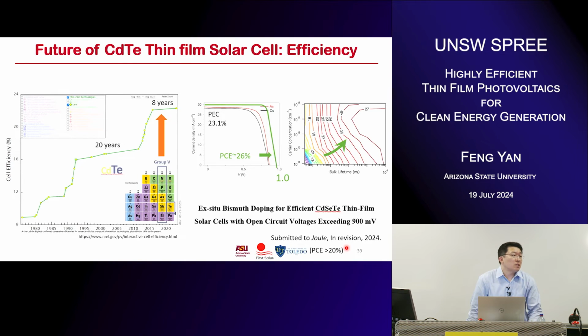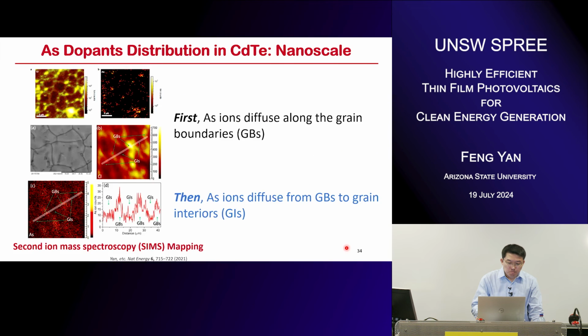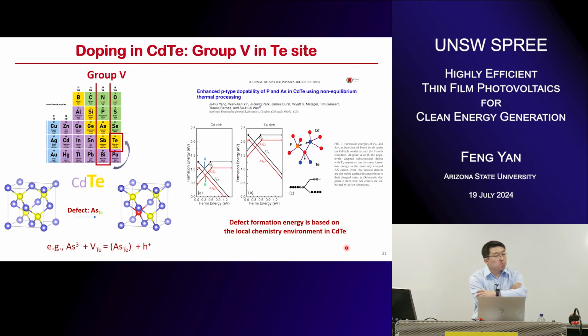I mean, which element do you find is better for the doping, and what's the main function? Because as you said from the beginning, in polycrystalline cadmium telluride the main problem comes from the grain boundaries, because you have a lot of grain boundaries compared to mono grain. So does this doping help to passivate the grain boundary, or help the grains recrystallize? Yes or no? Yes means that